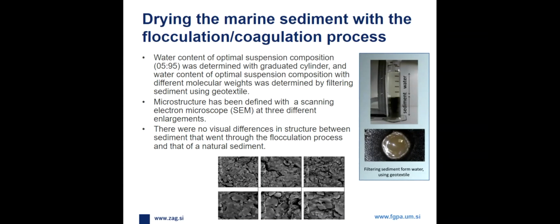Will the behavior of the material change, the mechanical properties, and the rest? We did some deeper analysis, and if you see those SEM photos from the microscope, the structure does not seem to change very much, either we use some flocculants or not. Probably the reason is that adding this kind of polymer is just a temporary change. The particles stick together for some time, and after it settled down, if we load it, this structure seems damaged immediately. It crashed, and we have the same material as previously.